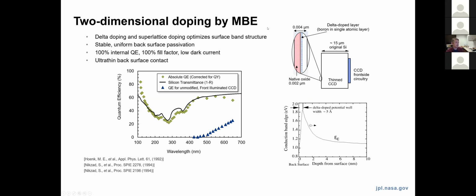I'll talk a little bit more about this molecular beam epitaxy approach. Some of the important considerations here are that this structure that we're creating on the backside of the device is also only a few nanometers thick. So we're still compatible with the very shallow absorption depth of the ultraviolet photons. And so by eliminating that potential well, you also eliminate some of those stability issues that were highlighted on the last slide. So not only do you recover the quantum efficiency that is lost in a normal front or back illuminated CCD, you also get this improved stability.